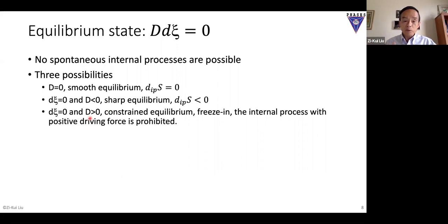Another one is that you do have driving force, but the process cannot happen. We call it constrained equilibrium. That's the one we see most of the time in our life, right? For example, the steel we use. Steel is constrained equilibrium because steel should oxidize, right? Aluminum should be oxidized. All the metals, most of them except gold and silver, should be oxidized, but they don't. Why not? Because of constraining. That constrained equilibrium is actually what we see the most. We have driving force, but the process doesn't take place.